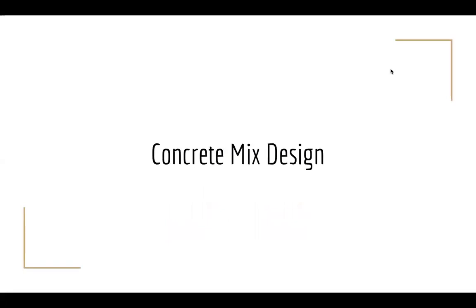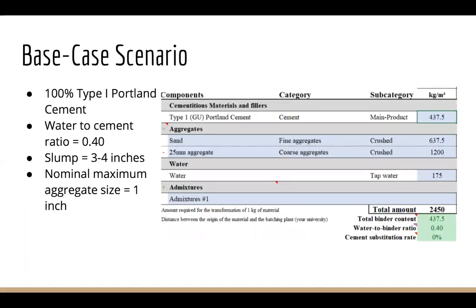To get started, we're going to talk about our concrete mix design. So for our base case scenario, we used 100% type 1 Portland cement. All of our values were determined using the PCA manual and the requirements set by the rules for the project. Our water to cement ratio was 0.4. Our designated slump was 3 to 4 inches, and we chose a nominal maximum aggregate size of 1 inch.